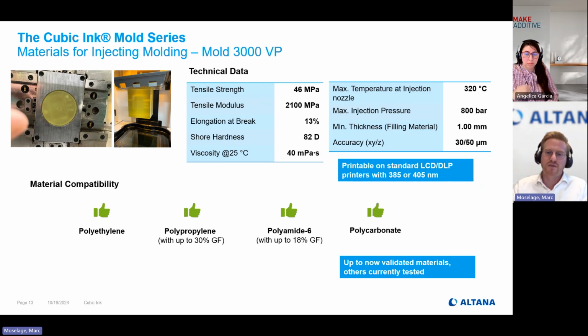Here it is also important to mention the minimum thickness we finally have, not of the mold, but what the final material in the end can have. And here we say 1 millimeter minimum thickness of the filling material is well tolerated, because if you go lower, the sweating behavior is not fully avoidable, but 1 millimeter, generally speaking, is well feasible. Here, for this case, we are talking about PA6 with glass fiber filling. For other materials, maybe lower thicknesses can also be tolerated. The accuracy is pretty good, 30 microns in XY, and 50 microns in Z, depending basically on the printer and the layer thickness you print.